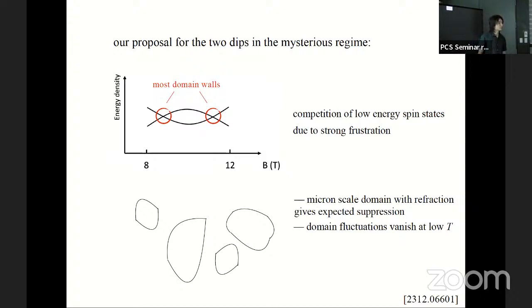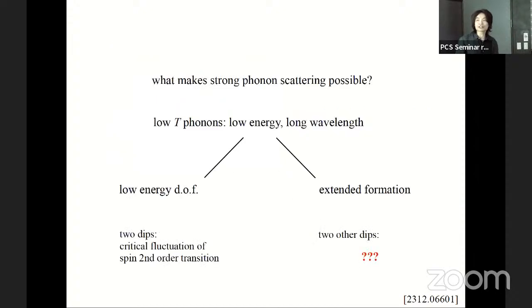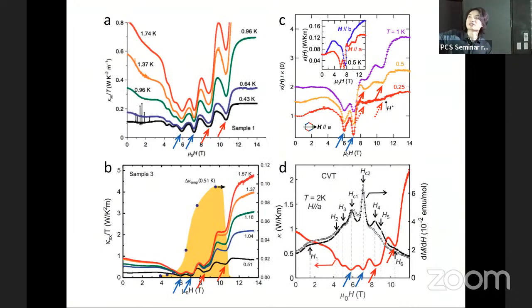What I got confused with was that you mentioned in the earlier examples, because of the resonant scattering, the value of kappa was large. Wasn't that what you said? No, it's not that the value of kappa is large, but the temperature scaling of kappa is lower than T cubed. Okay, I see. Here in this material, in this large magnetic field part, it goes roughly like T cubed. In this part, the temperature dependence is more complicated.